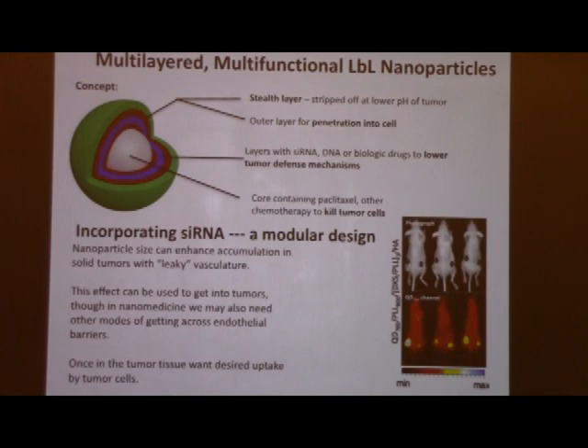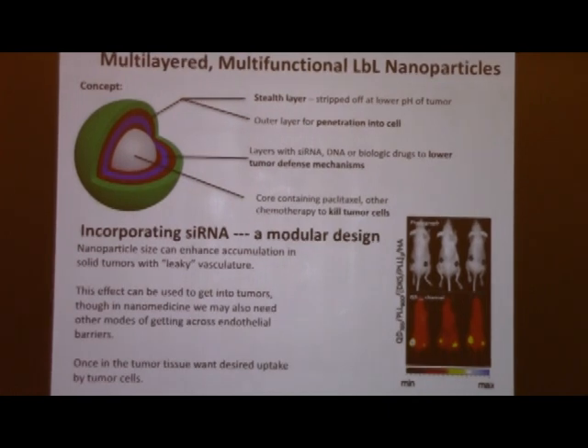So if you have a nanoparticle that is 100, 120 nanometers or so in size, the belief is essentially that when you introduce the nanoparticle into the blood vessels, the nanoparticle will navigate the bloodstream, and if it can stay in the bloodstream long enough, will end up in the blood vessels that belong to the tumor. And when it gets into the tumor, it will go through those leaks and actually get caught in the tumor before it finds another leak to go out in.